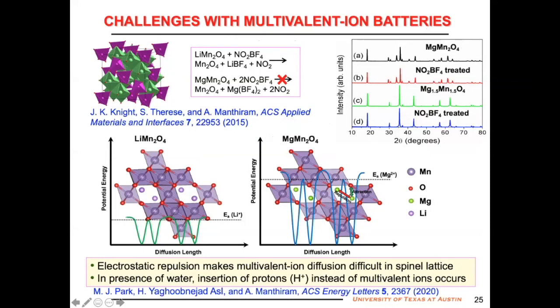Multivalent ion, again, oxides are useful, but if we take close-packed oxides, multivalent ion diffusion is a big problem. Sometimes in my group, we do simple chemistry experiments to learn a lot. For example, if you have LiMn2O4 and treat with NO2BF4, you can remove all the lithium out, no problem. If you have the same structure, everything same, MgMn2O4, and treat with NO2BF4, no magnesium can be removed. X-ray pattern you can see here, you can analyze magnesium content. Nothing happens. Why? Magnesium 2+ has a hard time to move from the tetrahedral site to a neighboring empty 16c octahedral site to the next tetrahedral site, so it doesn't want to move.